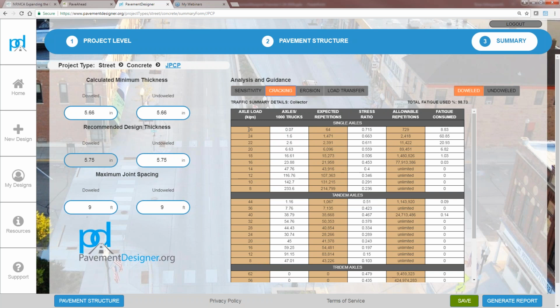So we see on the left-hand side our axle loads, number of axles per 1,000 trucks, for our single axles, our tandem axles, and then our tridem axles. And if you look on the far right-hand side, it shows that our 24 KIP single axles consumed about 61% of our fatigue, and the 22,000-pound single axles consumed about 21% of our fatigue. So those are the 2 axles that are doing the most damage to our pavement. But what we see is that there's very few of those axles. There's only about 1.6 and 2.6 of those axles per 1,000 trucks, but they do the most damage.